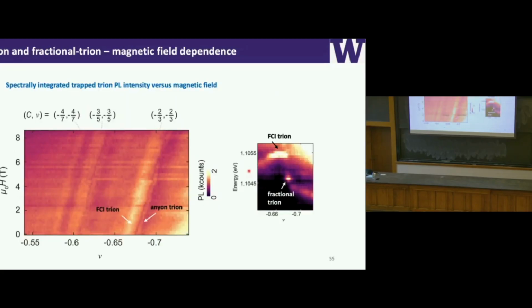And we can also do these Landau fan diagram measurements again, right? In the data, what I show you here is that I do a spectral integration of these features and plot it as a function of magnetic field on the vertical axis. Now we can focus on the 2/3 filling, right? We see that there's a wider, broader feature, and there's a narrow feature. Both of them actually have the same slope, 2/3. So the broad feature is from the FCI state, and this narrow feature is actually from the anyon-trions.